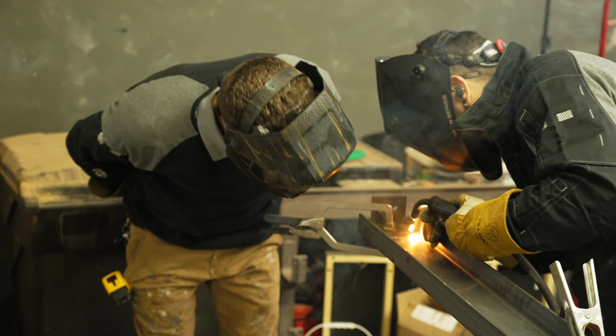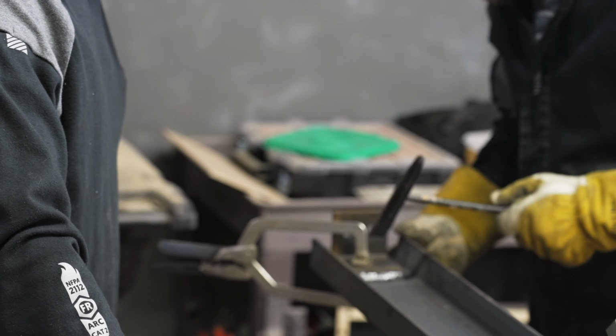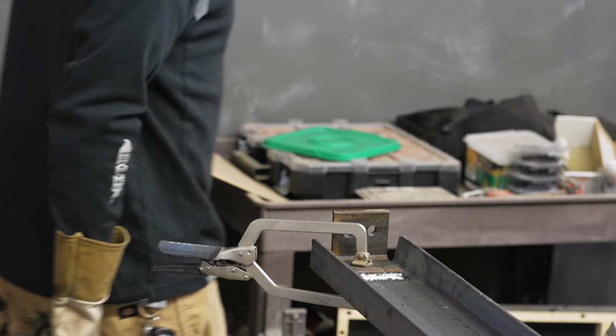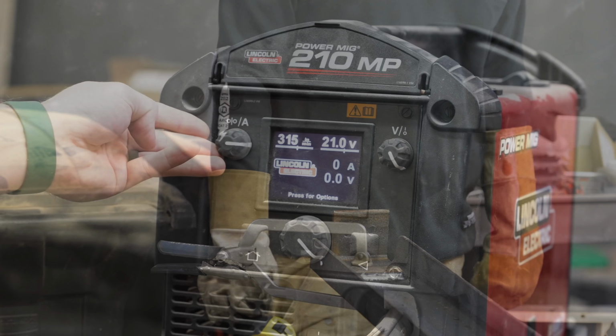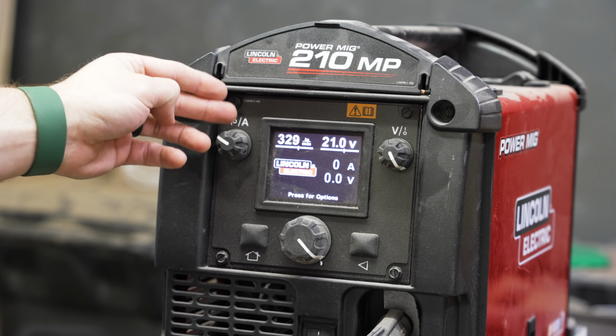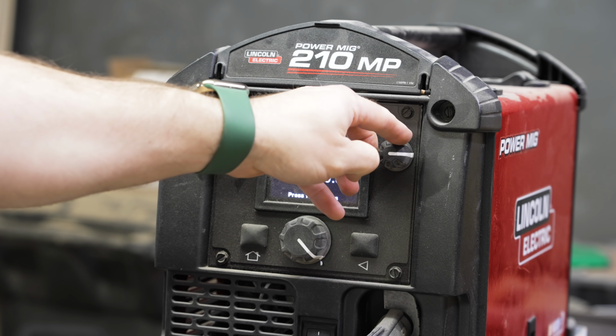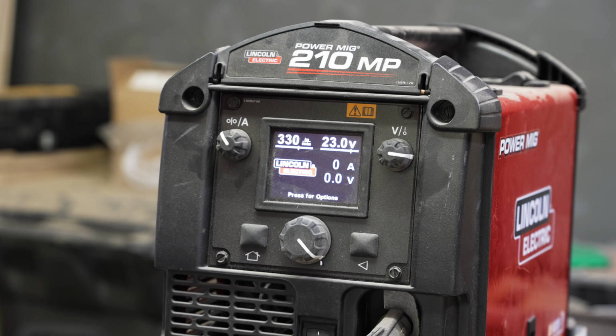And the first couple of welds were looking pretty good with these settings, but we bumped up the wire feed and voltage just a bit, as it seemed like we could push the speed a little more, and this helped a lot. And we ended up at around 330 inches per minute and 23 volts, and this seemed to be a pretty good sweet spot for this combination of steel.